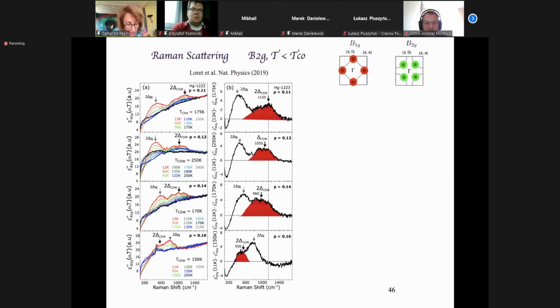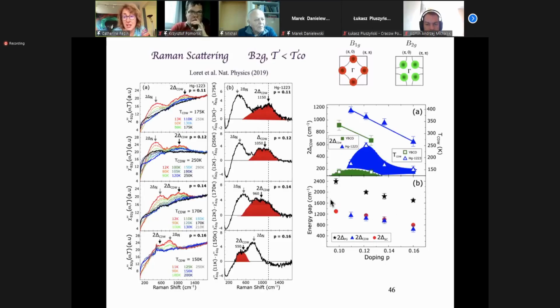I just go to Raman scattering, which is also a pretty nice experiment. You see, Raman scattering is nice because it enables you to scan the Fermi surface in reciprocal space. Basically, due to the symmetries of the Raman scattering, you can scan, let's say, the antinodal region of the Fermi surface with B1G and the nodal region with B2G. So in the antinodal region, you see the superconducting gap opening and the pseudo gap. And in the nodal region, in a recent paper, they claim that they can see with an excitation peak the value of the amplitude of the charge density wave gap, which is the only experiment which is able to see it so far. And very intriguingly, they saw that this amplitude, they claim the amplitude of the charge gap, is of the same magnitude as the one of the superconducting gap.